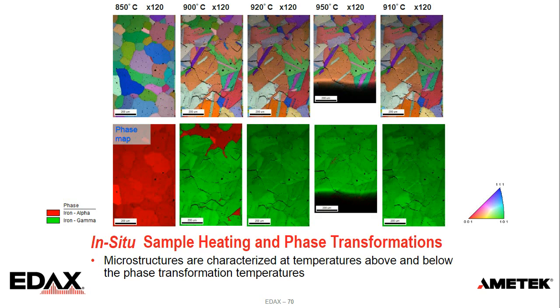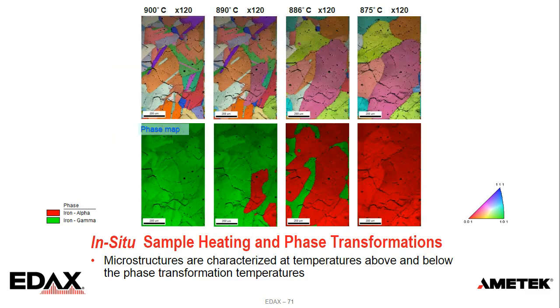Through all this, one of the things we can do is in situ analysis. This is an example, work by Suzuki-san over in Japan, where he's done heating of a steel through the transition temperature. We start here in the red, come up through it, it transforms into the green phase, and then as we go back down, it comes back to the red phase. We can control temperatures going up to the 1,000 degrees C range to be able to observe these transformations in situ.